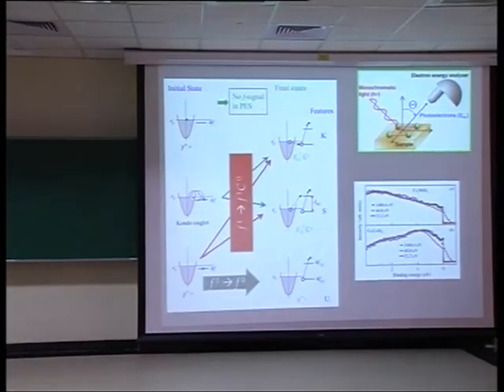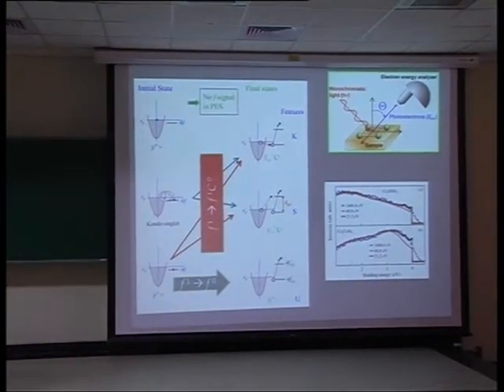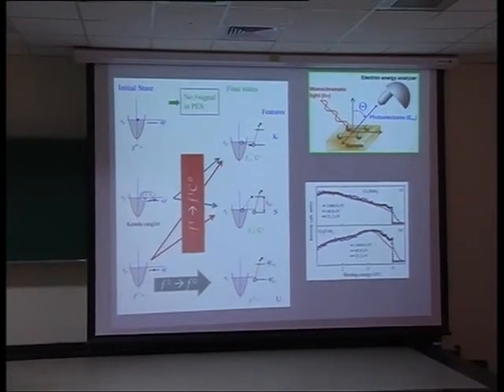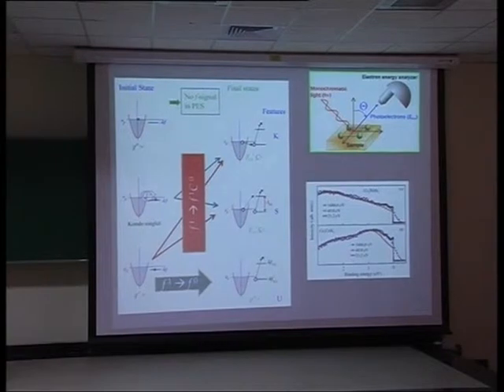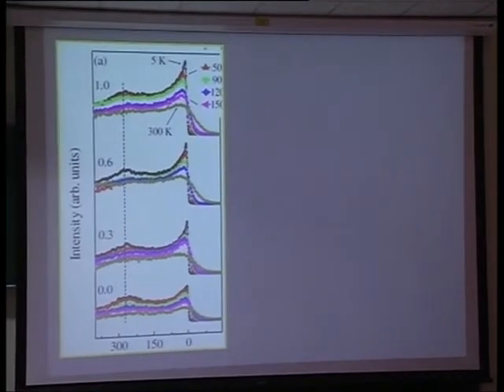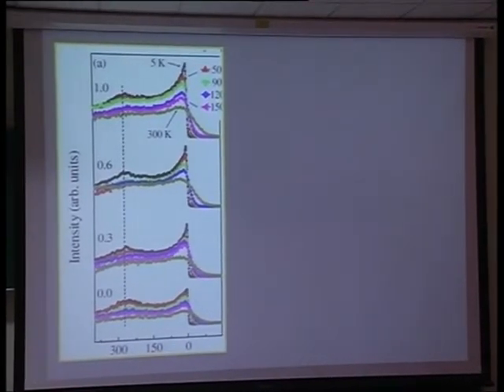So what you do is reduce the temperature, and if you see that the intensity of this feature grows with respect to this, then you are sure that there is a Kondo effect. This is a direct signature. So what we have done here is take the difference of the He II minus He I spectrum and plot it at different temperatures. This is the Kondo compound, which shows this Fermi liquid phase, and you see this feature which we call the Kondo resonance feature, and this is a spin-orbit coupling state. Both of them show temperature dependence; as you increase temperature, they go down in intensity.